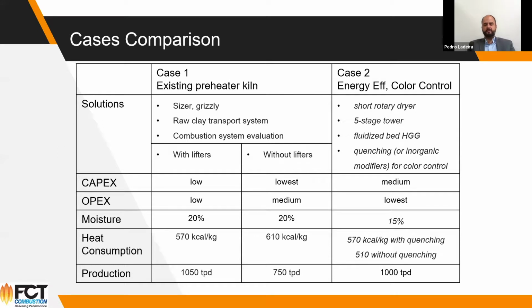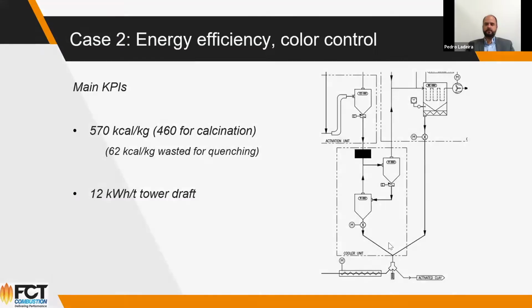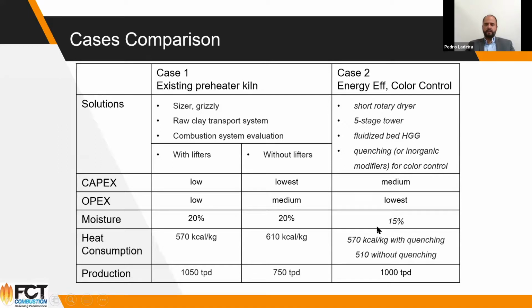And if we compare those cases that we've presented before in a qualitative way, we can say that case one with existing preheater kiln, you're going to have a lower capex compared to these, no lifter changes. And it's going to be the lower capex, but of course a lower capacity as well. On OPEX, you're going to have low, medium, and the lowest one being the flash calciner. These are different scenarios, and you have 20% moisture, and then you have 15% moisture. And the heat consumption as well, it all depends on whether or not you're going to apply the lifters for the case of the rotary kiln, and if you're going to apply or not quenching for color control. So we can be very efficient, but it can go as low as 510 without quenching for 15% moisture.